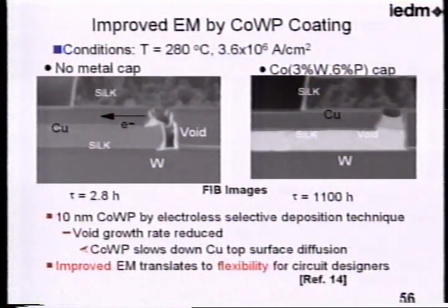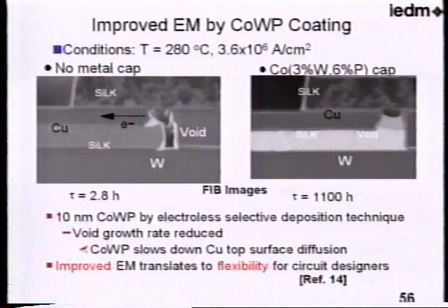To improve electromigration, some capping coat on the copper is effective because if we put some capping layer onto a copper interconnect, that will prevent the copper diffusion at the boundary surfaces. So in that case, cobalt tungsten phosphorus film was deposited by electroless selective deposition technique. And these pictures correspond to the failure mode. This case is no metal cap, and this is a cobalt cap sample. So this kind of improvement of a copper interconnect and also the impurity addition is effective to improve electromigration reliability.